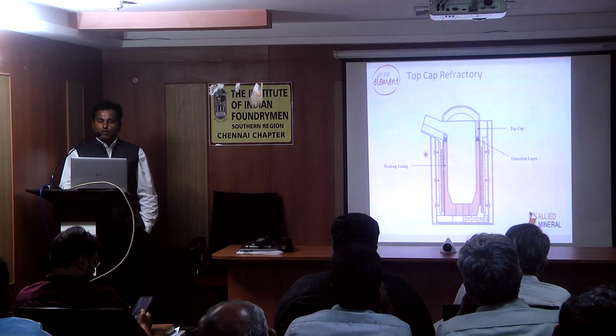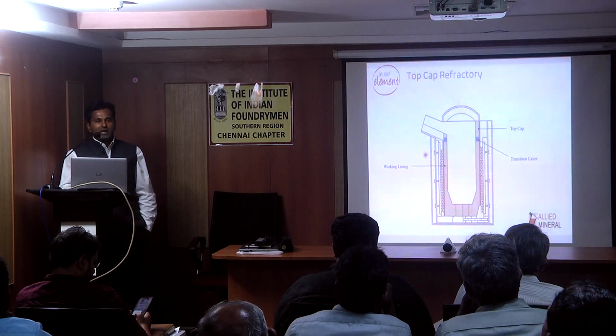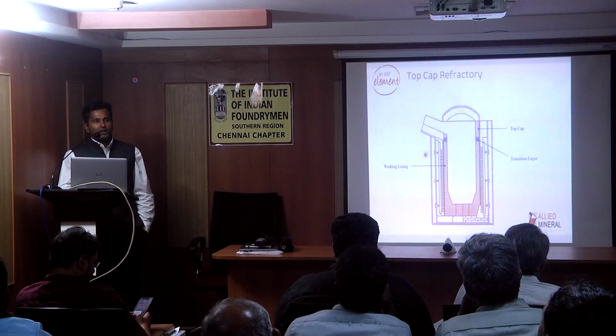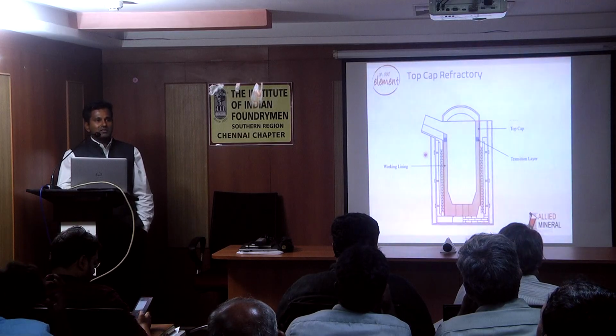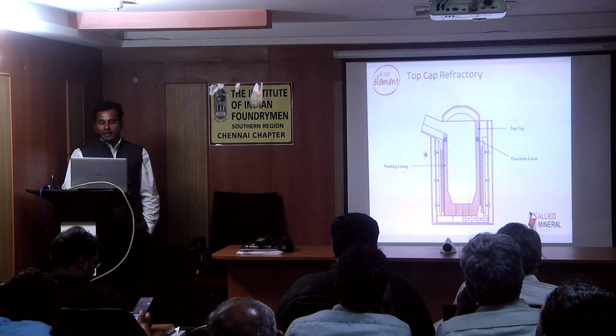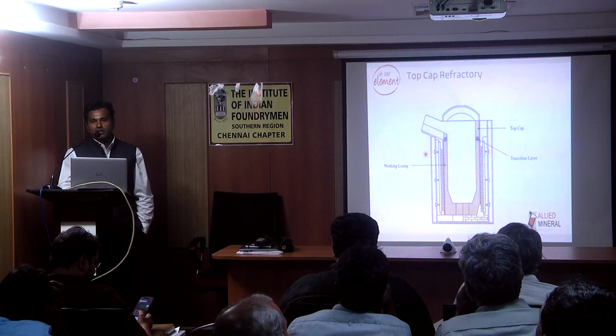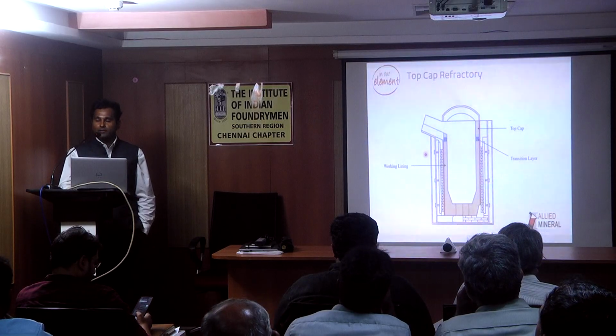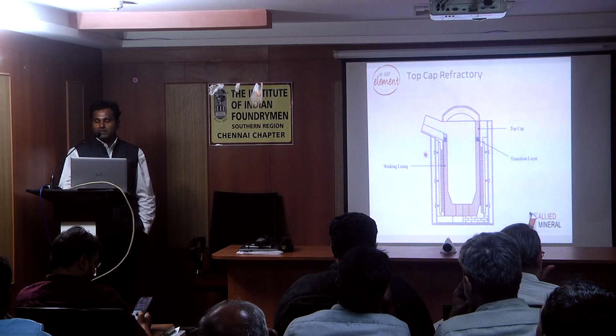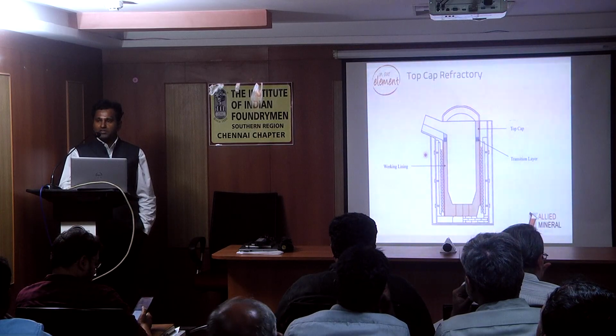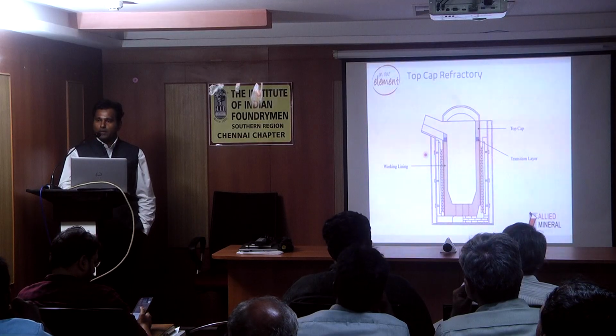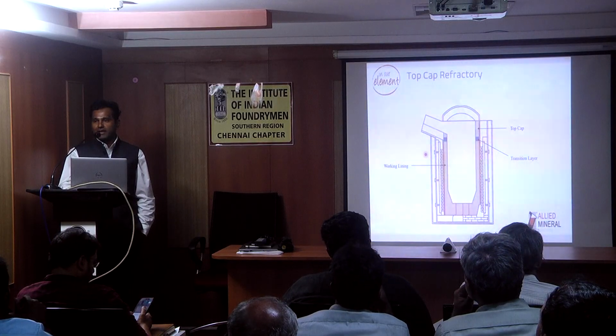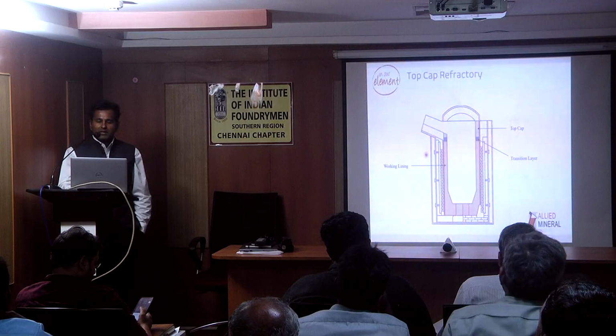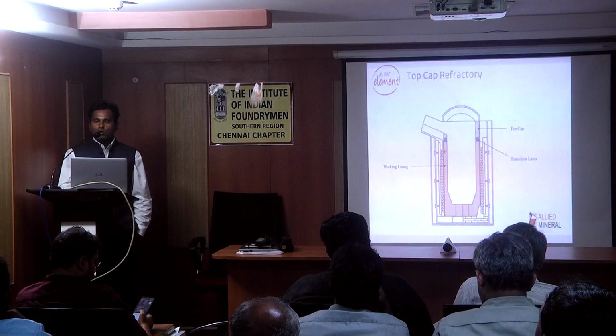So we recommend using a dry top cap, which has an additional binder to take care of the impact of your charge and the thermal shock, added with fused silica. Fused silica is a more thermally stable product compared to normal silica. So with these two ingredients, we can achieve a better strength and more thermally stable top cap, even though it is dry. So how do we install it on top of your power coil level?